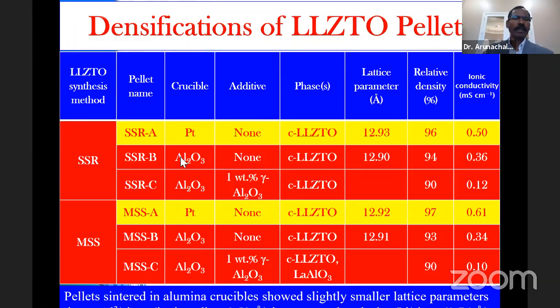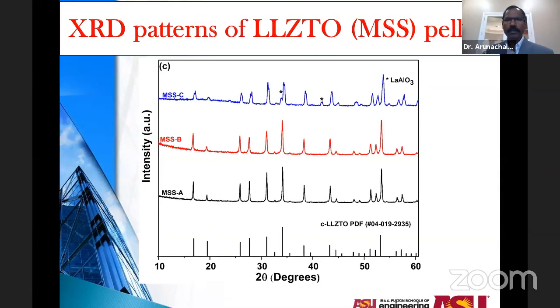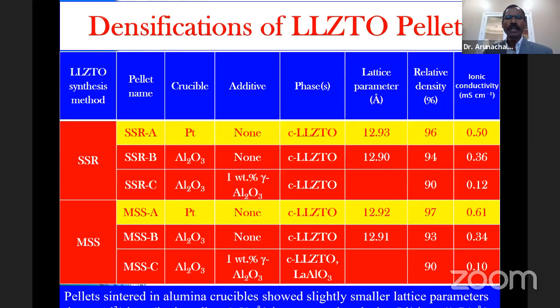So we had three different approaches. One is to sinter the pellet in a platinum crucible, another variant is to sinter the pellet in an alumina crucible, and another is sintering in an alumina crucible but also adding a sintering aid. The sintering aid is mainly to improve the density, and all these pellets were covered with mother powder to avoid lithium loss during the densification process.